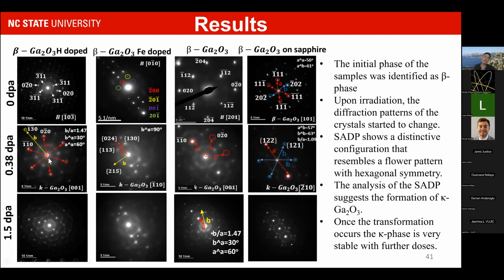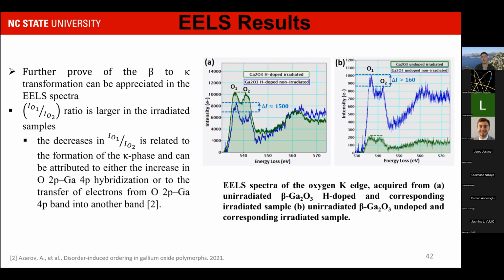But as soon as we started the irradiation, very quickly, less than 0.4 dpa, we start seeing extra spots and changes in the diffraction pattern, which, by the way, were indicative of phase transformation, when the phase is identified, in fact, as kappa gallium oxide. And what we observe is that by irradiating further, that phase was not changing. It's pretty stable. Thermodynamically, it's a metastable phase because the beta phase is the one that thermodynamic equilibrium predicts.